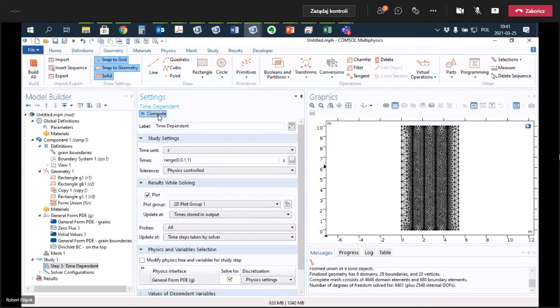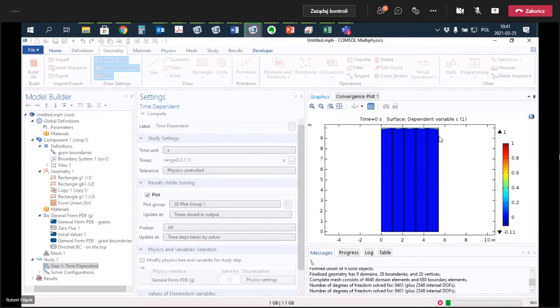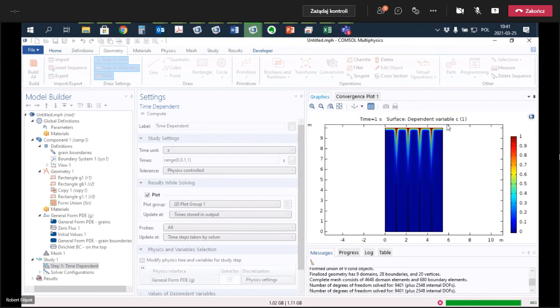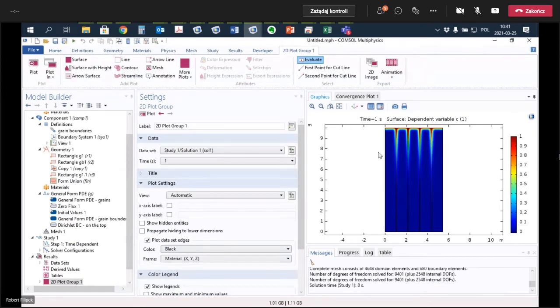And let us repeat our computations. And now you can see what the progress in concentration is in this material's microstructure. So you can see that color corresponds to the value of the concentration. So red is the highest concentration, 1, and blue is the smallest, 0. And as you can see, mainly transport occurs through the grain boundaries, because the diffusivity is 3 orders of magnitude higher. In the grains, there is only a very small region of diffusion, for the same reason, that the diffusivity of the grain is much smaller than on the grain boundary.